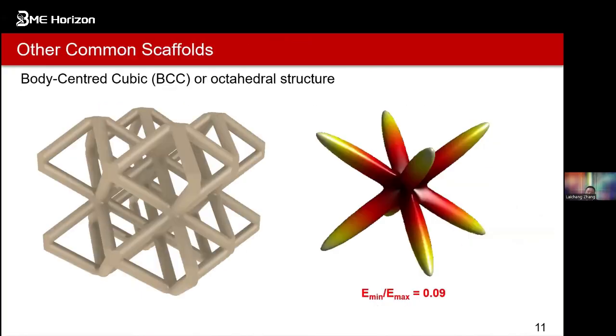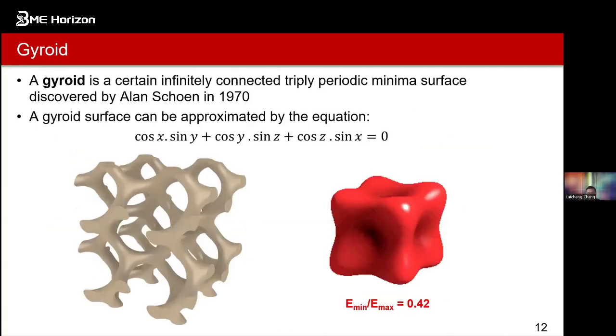inhomogeneous structures. But we can also use the BCC structure. This structure has also been commonly used, but it is even worse in terms of non-isotropic stiffness. You can see the minimum to maximum ratio was roughly 0.09, so 9% of the stiffness. Another one is the gyroid structure, which has also been used. It is better and has better homogeneity in stiffness. You will see the minimum and maximum stiffness ratio is roughly 0.42. But we still say this kind of structure is not sufficiently isotropic.